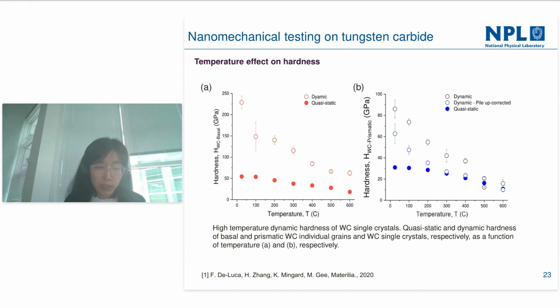The difference between quasi-static hardness and dynamic hardness is not very clear, but it could be from a change of the deformation mechanism. We also observed, for the impact test on the prismatic grains, that when the temperature is above 200, large plastic deformation was observed.